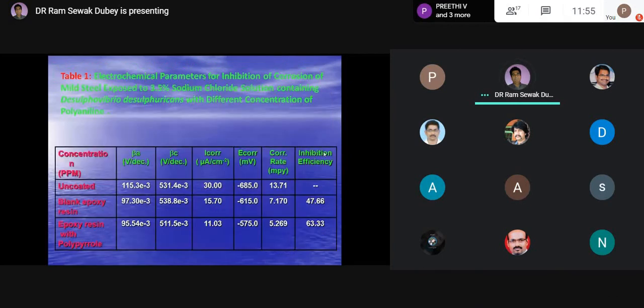This table indicates different electrochemical parameters: beta A, beta C, I corr, that is corrosion current, E corr, corrosion potential, corrosion rate in MPY, and finally inhibition efficiency. It was observed the blank was containing 47%, but when it was impregnated with polypyrrole, it's giving 63.33% inhibition of the corrosion, as well as inhibition of the microbial population also.